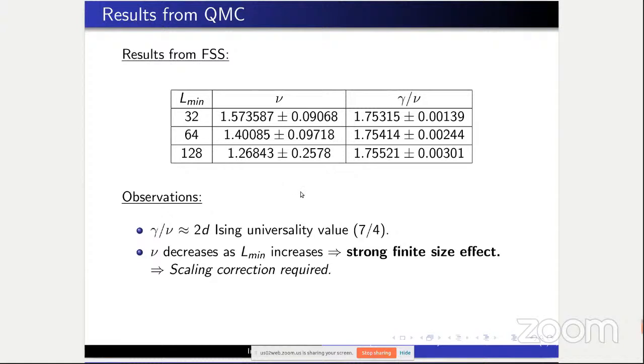And here we can observe that the gamma by nu ratio is close to the 2D Ising universality value, which is 7 by 4, and the values of nu decrease as L min increases. So this shows a strong finite size effect. So we have to incorporate scaling corrections to find the precise value of this critical exponent.